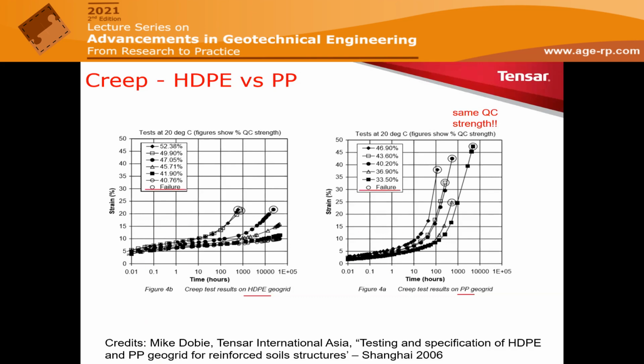So let's see the load at failure. Let's see what's happening at failure. And let's take this sample. So these are different samples that we test, or we creep them, at different percentages of QC strength. And let's look at two of them that are both at 47%. So if the QC strength, let's say, is 100 kilonewton, the HDPE grid is being tested in creep at 47 kilonewton, and failure occurs in 2 years, okay?